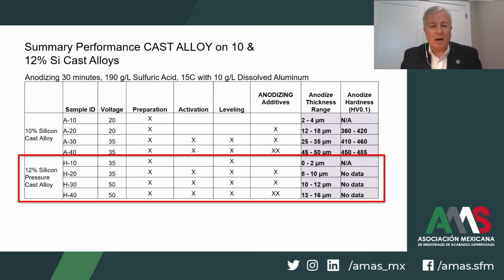Here, as shown in the red box, the data comparing H10 to H40, pressure cast alloys do have some limitations with oxide growth versus a gravity cast part, but still the incorporation of the acid activation and the leveling steps in the stage 1, while also increasing the additive package to the anodized solution, does maximize the ability to provide a much improved anodic layer to the pressure cast alloy. We cannot emphasize enough that understanding the impact of the casting method will always have an important consideration in the success of anodizing cast alloys.